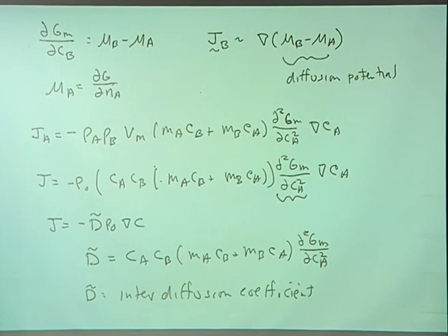And that is an interesting problem. Think about what's happening here. So, okay, I want to make sure that everyone understands. You have fluxes up composition gradients, but are the fluxes going up or down chemical potential gradients? Okay? And that's basically a failure of classic, simple Fickian diffusion. And we'll talk about the implications of that after the break. So thank you for the questions.